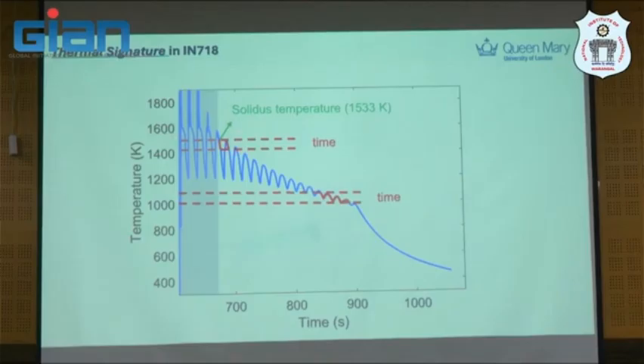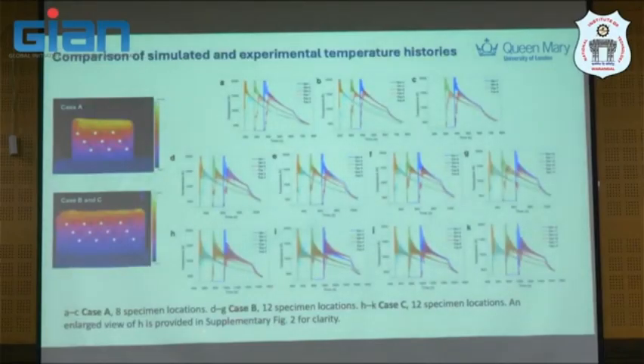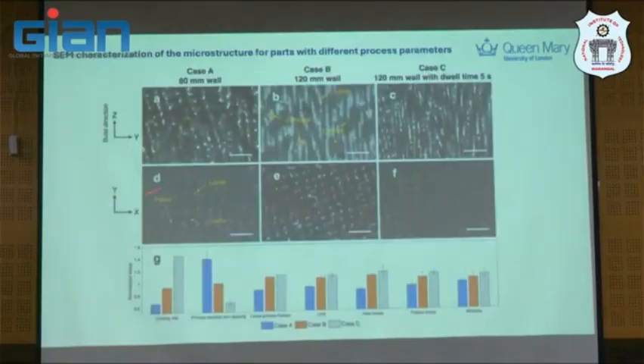there are about 5 layers that melt down into the substrate, I mean, underneath the layer. And this specimen has been carried out to compare simulated and experimental thermal history. So you will see different locations as well, here 12 and 8 locations. What this says is that for case B, when A, B, and C are as follows, the microstructures that result from these are different, and they have different cooling rates. As such, they get different primary arm spacing, and then they can approximately calculate the Laves phase, which is a detrimental phase, for each condition.